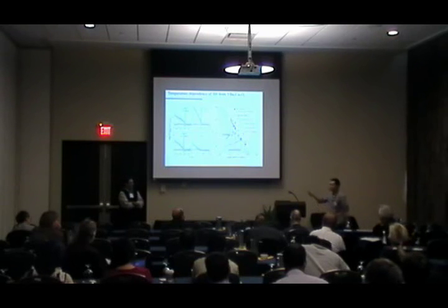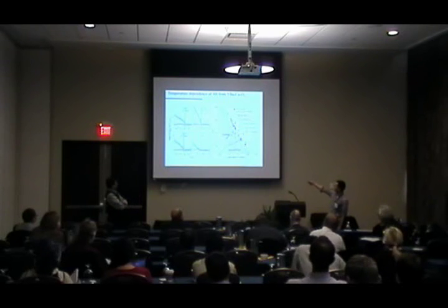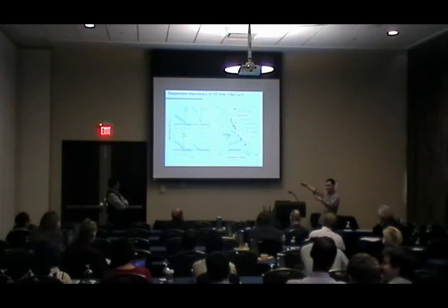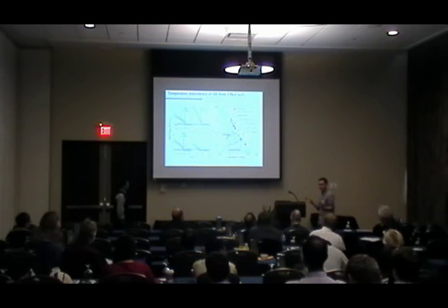That's a really good question. And what I'll say might be controversial, I'm not sure. But if you look at, let's take one of these curves. Let's look at this one in optimal doping, where T star is just a little bit above Tc. In this case, as you pull down, you cross T star, you cross this X-ray diffraction data that shows a charge order, and then you cross Tc. And in all of our data sets, it shows this order parameter. It doesn't look like it cares at all about Tc, it doesn't care at all about TCDW. It's something that's very independent of it that happens to terminate somewhere near optimal doping.